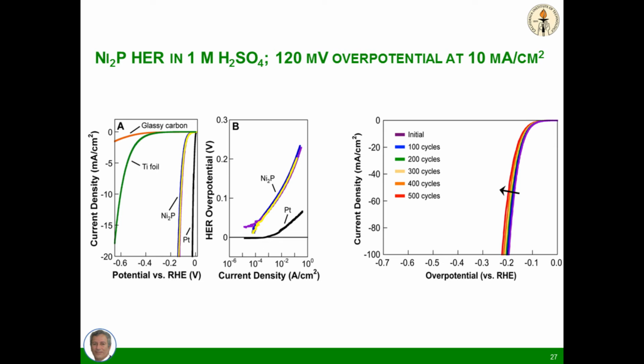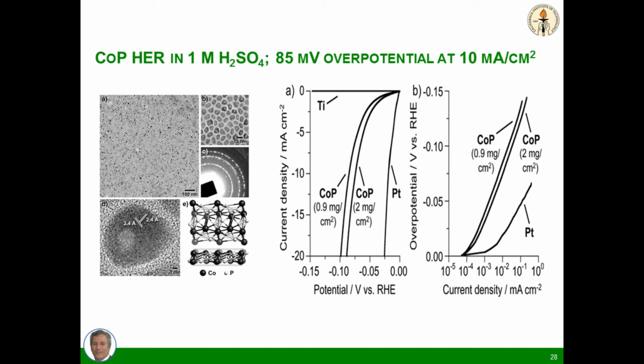We then took a lead and said, well, if nickel phosphide is an acid-stable, earth-abundant metal hydrogen evolution catalyst, what about other metal phosphides? We made cobalt phosphide. It was even better. We made iron phosphide. It was even better. And we published a series of papers of this nanomaterial synthesis by design. The reported best system is a blend between a metal sulfide and a metal phosphide by Tom Jaramillo's research group at Stanford, that has shaved another 30 or 40 millivolts off of the cobalt and iron phosphide systems, that has basically taken this entire class of compounds and shown that we don't need to use the platinum.